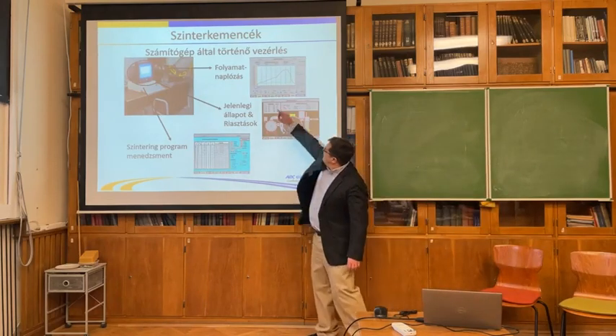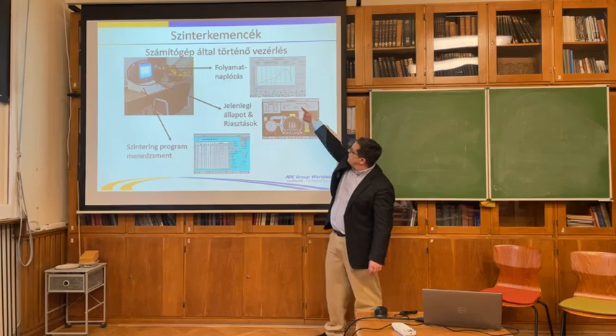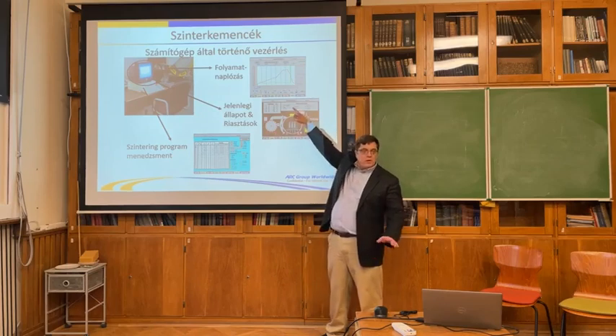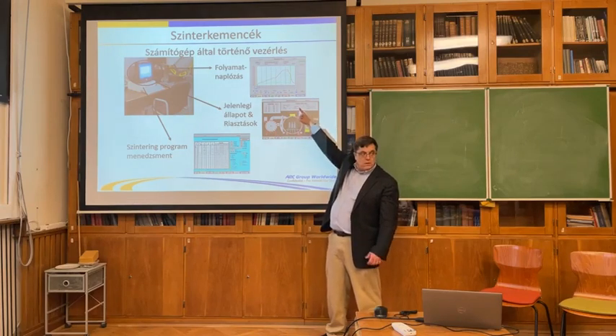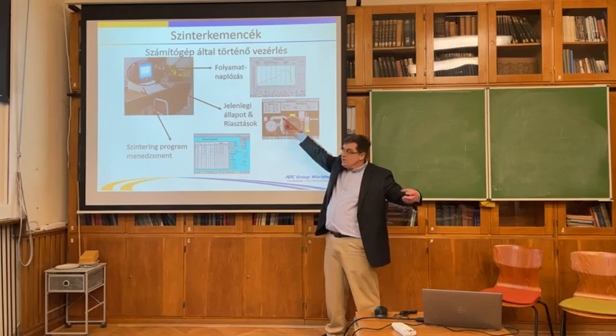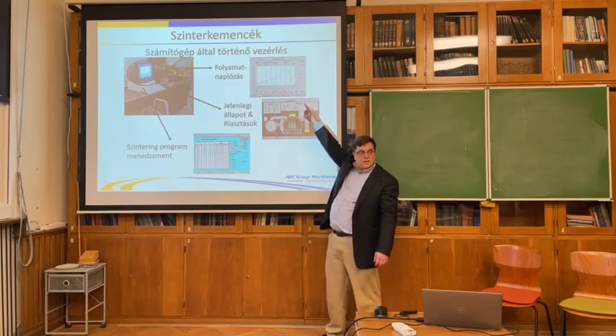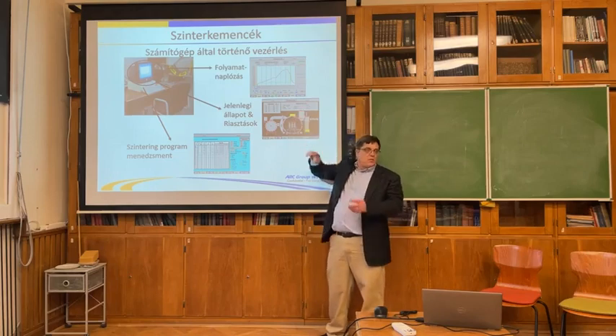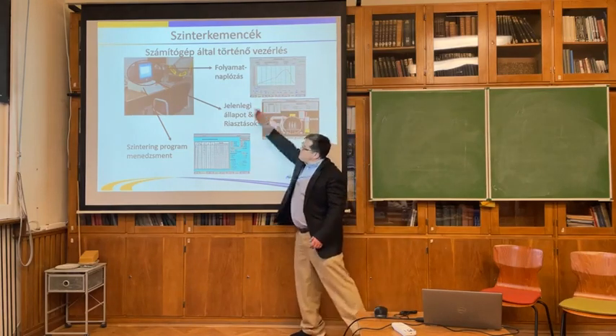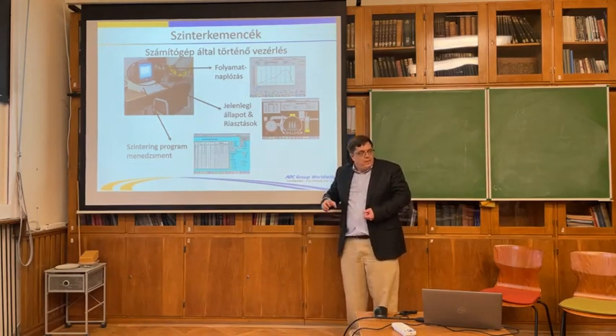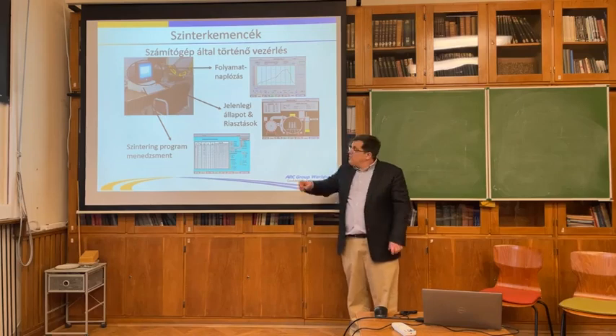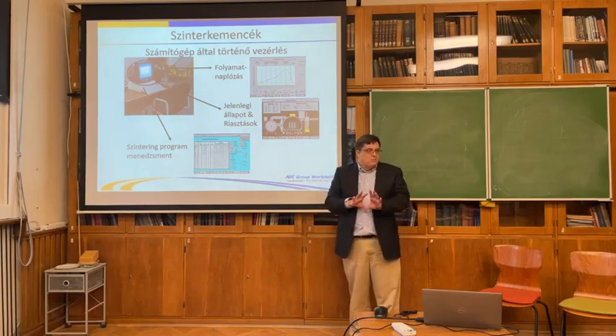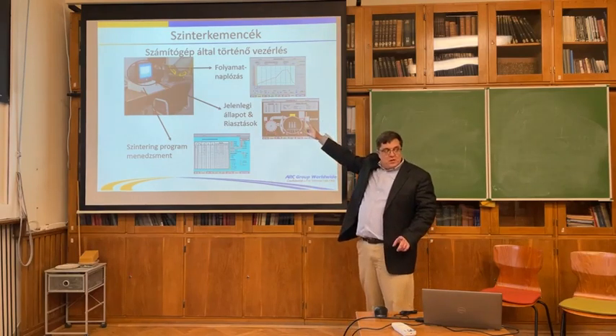So what's happening up there? That's what we call our sintering ramp. Once the door is closed, it starts pumping down the vacuum, and then the temperature starts going up at a pretty good rate, like 2 or 3 degrees centigrade per minute, and then it'll do a hold for an hour to let the temperature soak through the whole fixture. Then it'll go up to the next level, usually about 600 degrees. By the time it hits 600, almost all the binder is removed. In this first phase, the binder is slowly coming out, and we have a trap where it gets caught. So by the time it hits 600 degrees, it's pretty much all metal, but the elevated temperatures are keeping its shape. But it hasn't started shrinking yet.